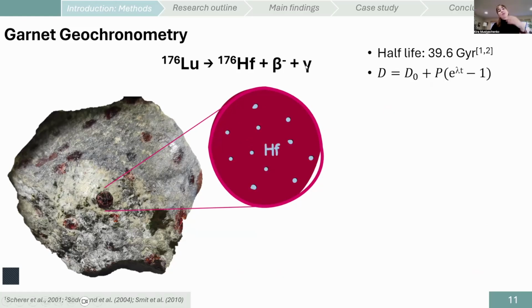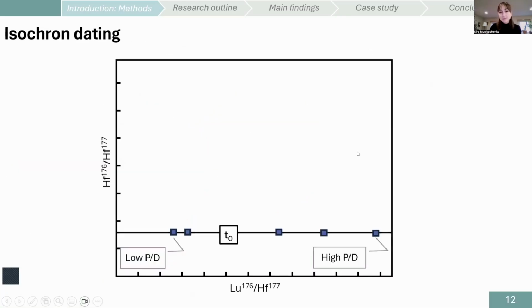The lutetium is slowly decaying into hafnium. Garnet doesn't like hafnium as much, so it doesn't naturally incorporate so much hafnium, making this value very low. But then this hafnium remains trapped in garnet, and that's what we can measure to back calculate the time where this accumulation started. To do that, we use the concept of isochron.